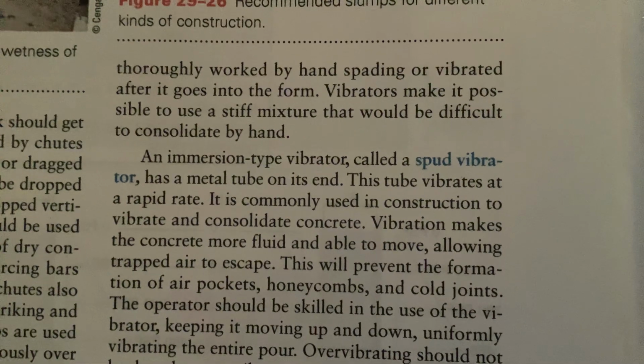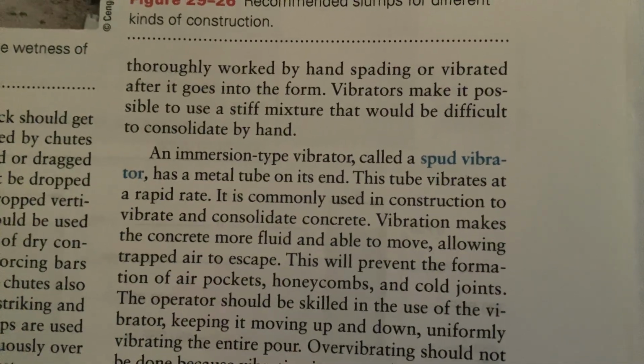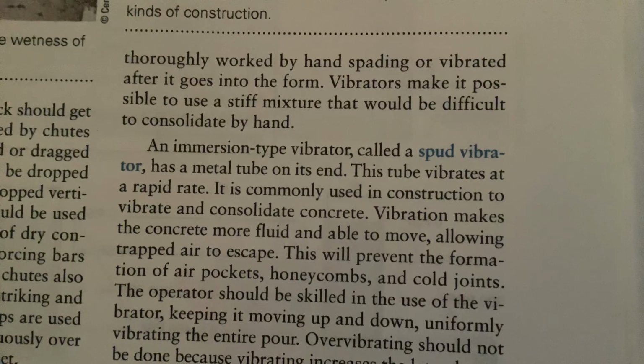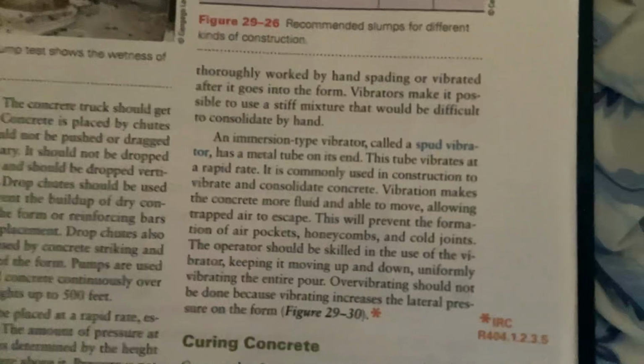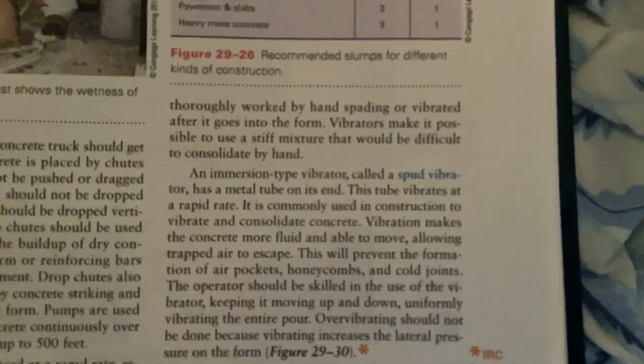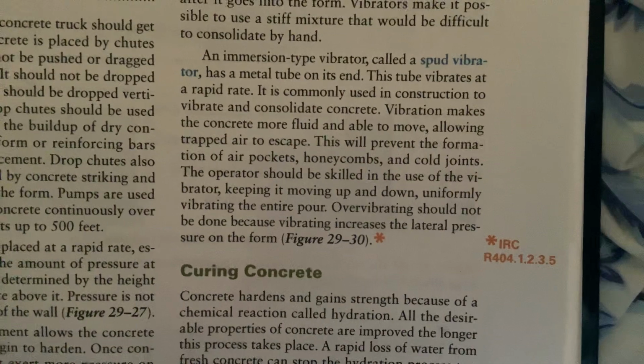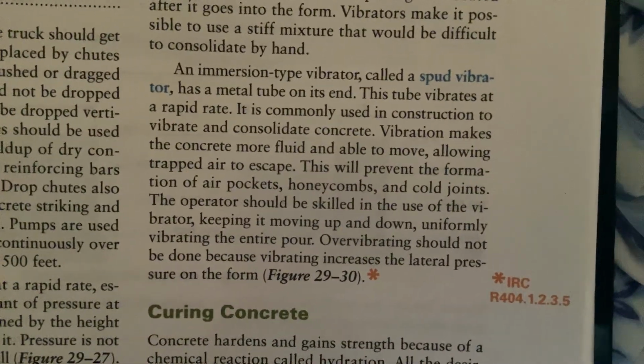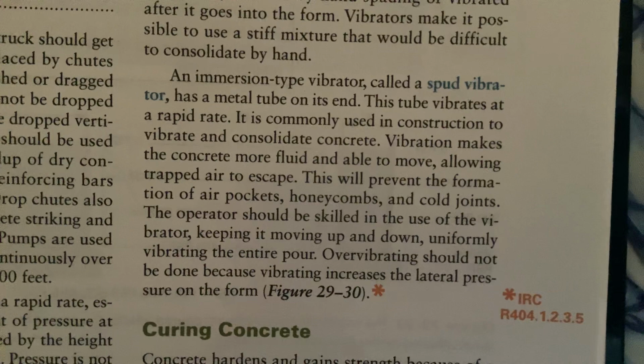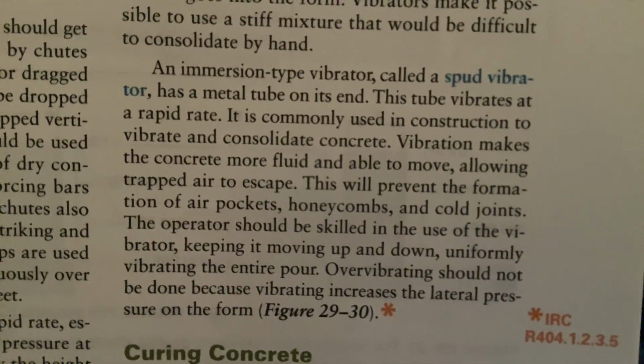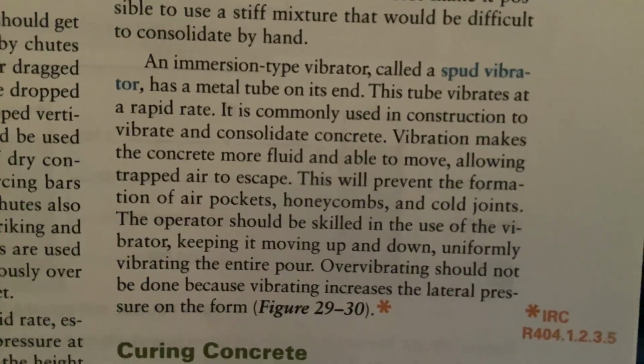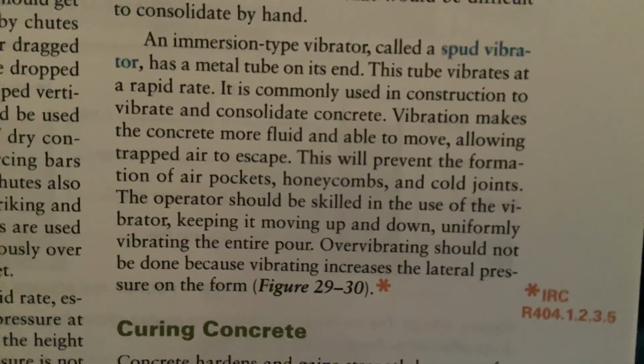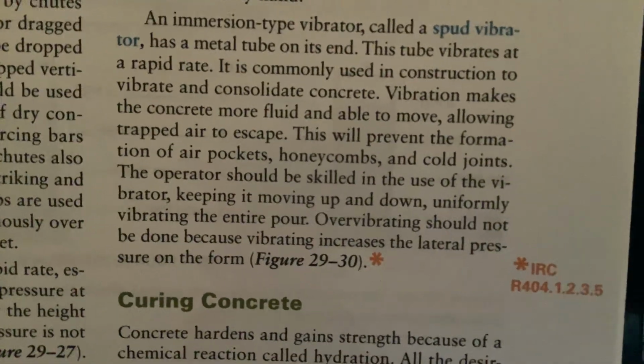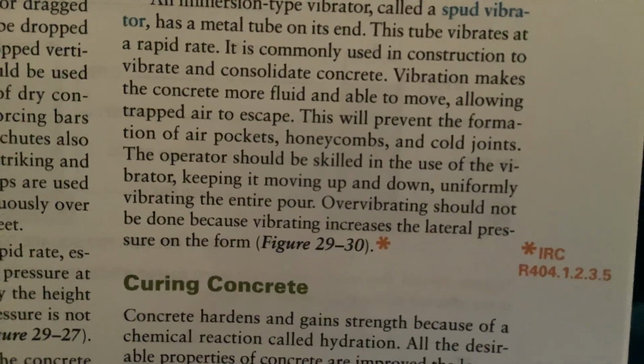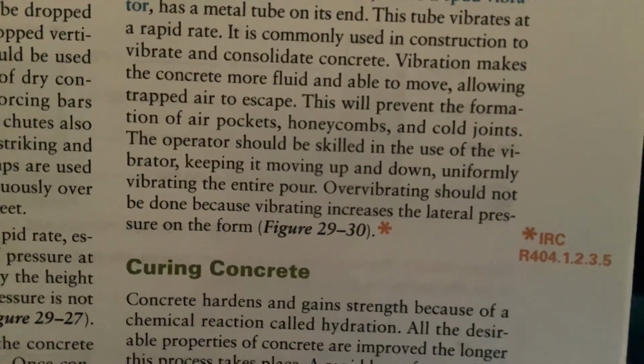Be thoroughly worked by hand, spading, or vibration after it goes into the form. Vibration makes it possible to use a stiff mixture that would be difficult to consolidate by hand. An immersion type vibrator called a spud vibrator has a metal tube on its end. This tube vibrates at a rapid rate. It is commonly used in construction to vibrate and consolidate concrete. Vibration makes the concrete more fluid and able to move, allowing trapped air to escape. This will prevent formation of air pockets, honeycombs, and cold joints.